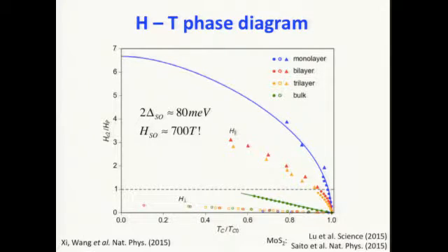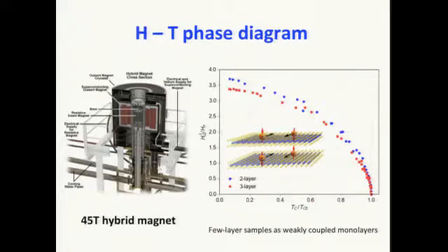Yeah. You're talking about essentially why the two- and three-layers also go way beyond the dashed line. Yeah. So basically we can extract, by fitting the pair-breaking equation, a spin-orbit field of about 700 Tesla, which actually agrees pretty well with the first principle calculations of the Fermi surface. Okay, that's also related to your question in this slide.